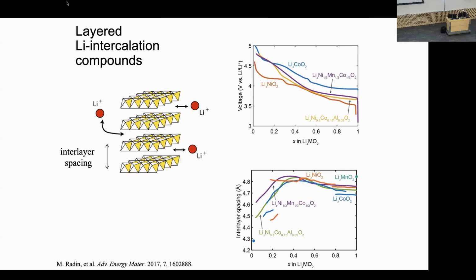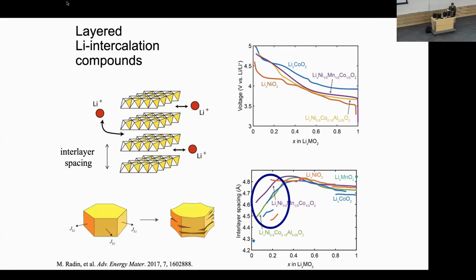So there's a dramatic drop in the C lattice parameter. And the effect of that is quite drastic. What happens is when you're pulling lithium out, you're depleting the surface of lithium, and that means the surface is at a low composition, and its lattice parameter wants to be contracted, whereas the interior of the particle is still lagging behind. It's still at this lattice parameter.